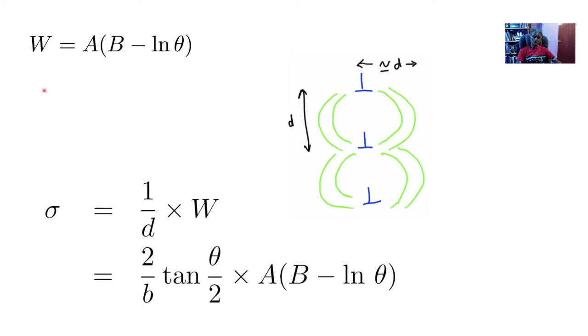So we have this equation once again, which is the energy per unit length of a dislocation in an array of dislocations defined by the misorientation theta. Now, suppose that we assume there's a unit length into the board, and we work out the number of dislocations per unit length along this direction. And of course, that number is just 1 upon the spacing d. Then multiplying this equation by 1 upon d gives me the interfacial energy per unit area. So in this equation, we have the interfacial energy per unit area in terms of the magnitude of the Burgers vectors of dislocations, the misorientation, theta. Very powerful equation. It's telling you how the interfacial energy varies as a function of the misorientation.